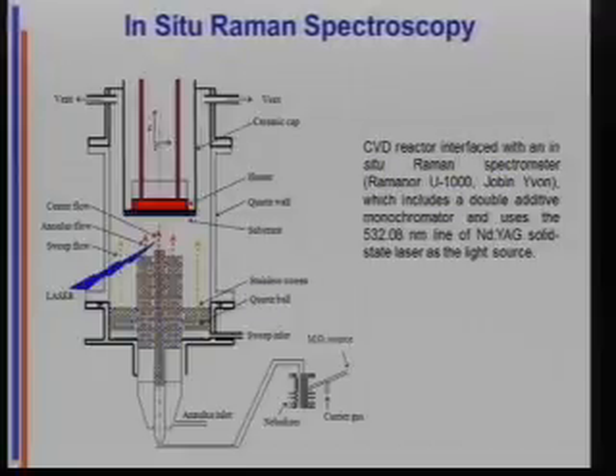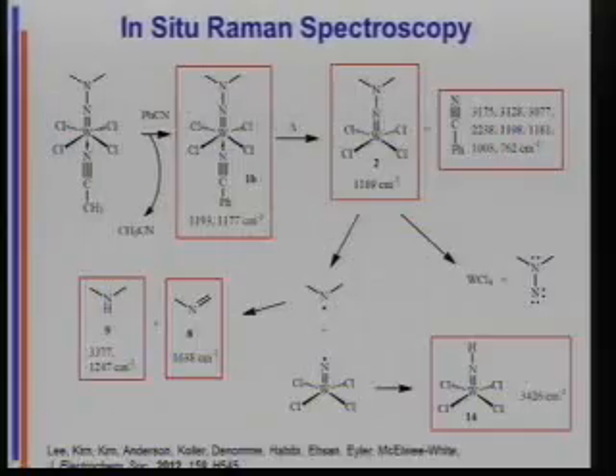Well, if you look at that hydroxido compound, we see a bunch of things. We're spraying from benzonitrile, so we see nitrile exchange. So this compound we see, and we can make authentic samples of that. We see another vibrational mode at 1189, which by DFT calculations is a vibrational mode of the hydroxido, the unsaturated one, so that's minus the acetonitrile. And then we see the coolest thing ever, which is these two compounds.